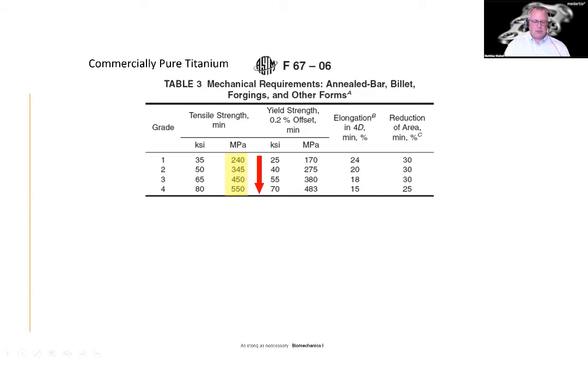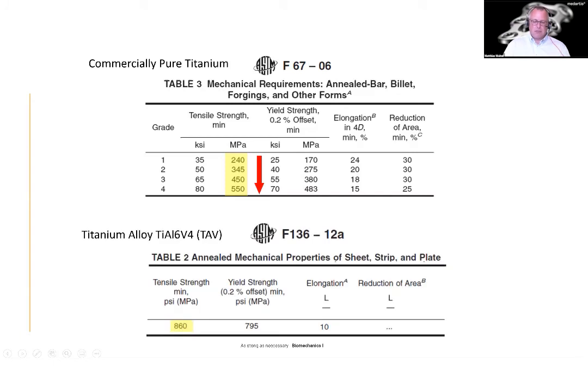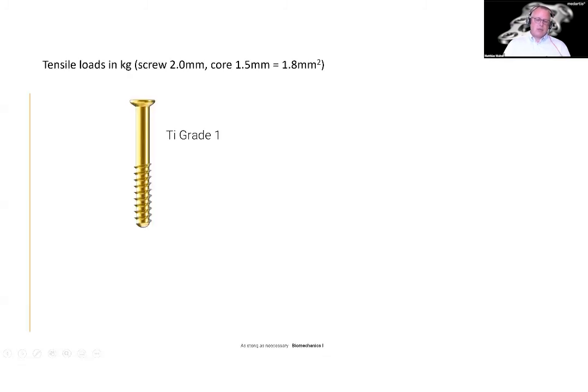If it would be made of titanium grade 4, then it would be 55 kilos. And it performs even better if you go to titanium aluminium vanadium, where you already have 86 kilograms that you could potentially lift. Now, the effect that this has on a product. When we look at, for instance, a screw, and this is just an example, a 2 millimeter bone screw with a 2 millimeter outer diameter, a core diameter of 1.5, and therefore a cross-sectional area of the screw of about 1.8 square millimeters, this screw would be able to lift about 43 kilos.